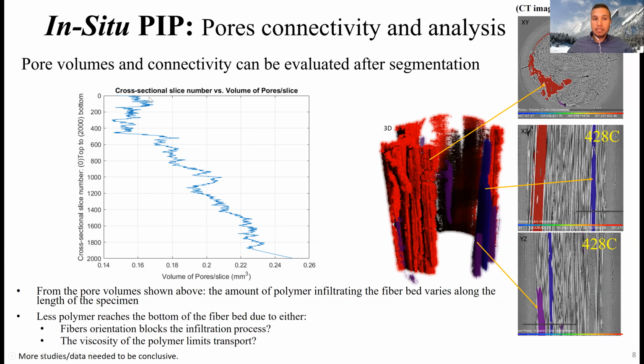But what becomes more interesting is when you look at the cross-sectional volume of the pores throughout the 2,000 slices in one CT scan. You can infer that the amount of polymer infiltrating the fiber bed varies along the length of the specimen. In this case, less polymer is reaching the bottom of the fiber bed. This could be due to the fiber orientation blocking the infiltration process, or the polymer is viscous and its viscosity limits its transport to the bottom of the fiber bed. Of course, more studies and data are needed to be conclusive on these claims, but this is part of the analysis that could be done after segmentation.